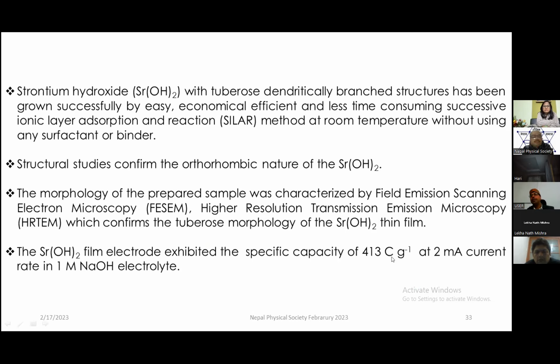There are two ways. The first one is that one can try doping with other materials. So we started doping, and we have done different dopings, and one can do composites also. Side by side we have done both things. For doping, we doped with copper, with iron, then yttrium and so on, to increase the specific capacity of this strontium hydroxide. And the second thing is that we try to make the device, because we have to make the device so that one can use it practically.